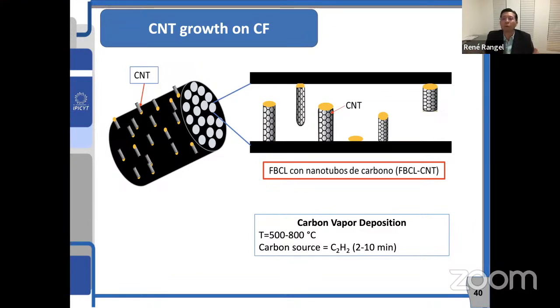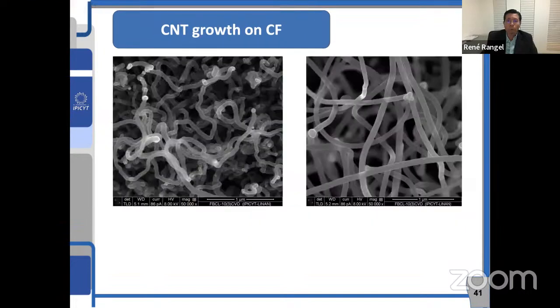Of course, we need to control the concentration and the temperature. As you see, we are using between 500 and 800 degrees to finally grow these carbon nanostructures as homogeneously as possible. So once we have that, we have a micrograph after a few minutes of these synthesized carbon nanotubes. These are already anchored, also very important, on this very nice carbon fiber.